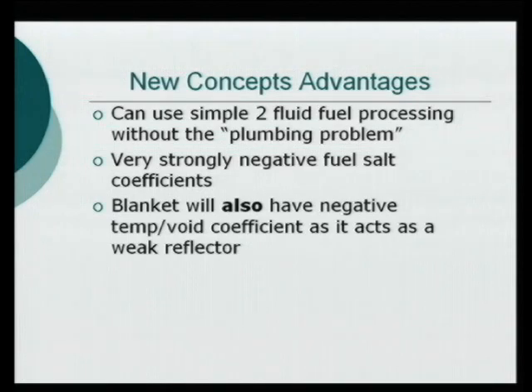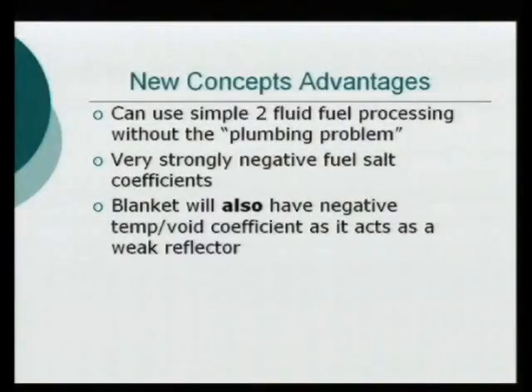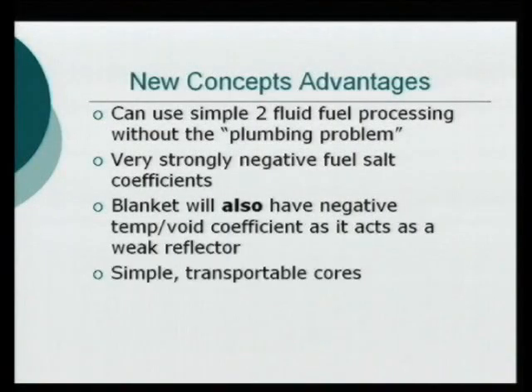The blanket salt should also be slightly negative, and Oak Ridge's design actually had a blanket salt coefficient that was slightly positive, because if it heated up, some of it was leaving the core. In this case, there's none in the core itself, just around, and it acts a bit as a reflector, so when that gets less dense, fewer neutrons will be reflected back, and it can slow things down as well.